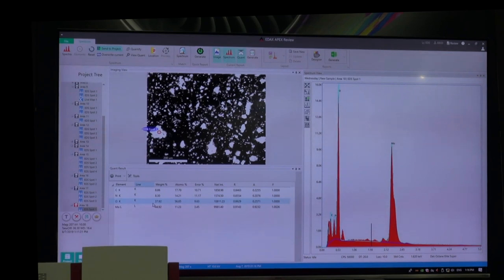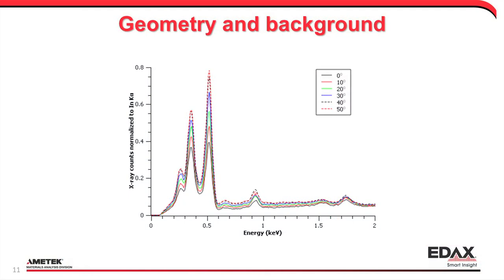It's one of the things we're probably going to add as a hint to users — if the tail doesn't meet the acceleration voltage, give it a big red pop-up box saying 'your sample is charging, are you okay with it?' Same thing with the low energy background: in principle, we can calculate whether your sample is tilted beyond what we read from the microscope. It requires pretty good statistics, but in principle we can calculate the effective takeoff angle from the misfit between the high and low energy ranges. There are distinct advantages to including the background in the spectrum.